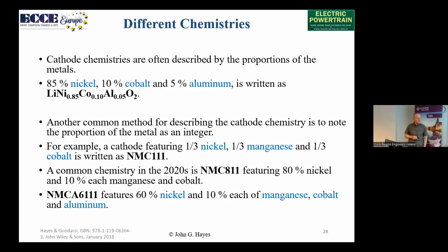Another way of using it is we describe the cathode as being NMC 111. So it's 1/3 nickel, 1/3 manganese, 1/3 cobalt. A commonly used technology now would be NMCA 6111, 60% nickel, 10% manganese, 10% cobalt, and 10% aluminum.